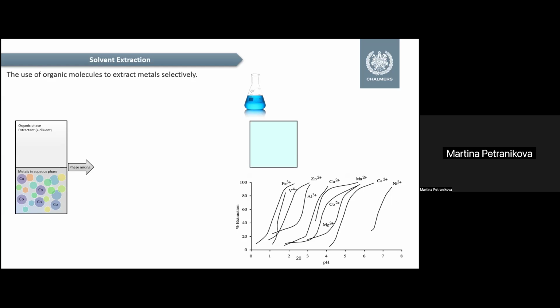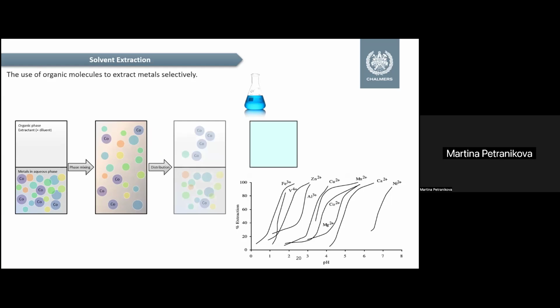So the principle is that we mix these organic molecules with our solution, and then the metal we want to extract usually gets into the organic phase. And since it is an organic molecule, it has a different density from the aqueous phase, so they get separated based on the different density. And then we wash these organic molecules, which contain mostly only the metal which we wanted to recover, with some clean acid, and then we get the metal in the clean form. What is very important, especially for people who are working with LCA, is to remember that these organic molecules are not consumable, so they can be used for many years within the process.